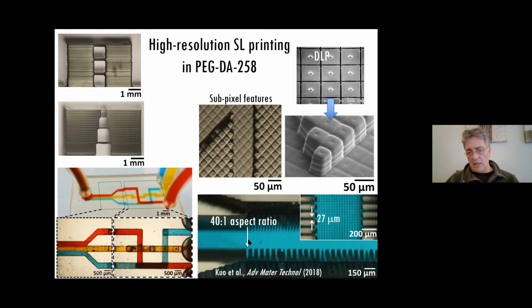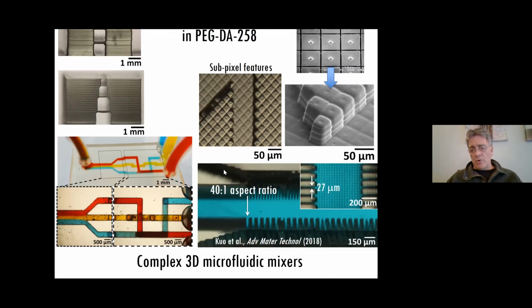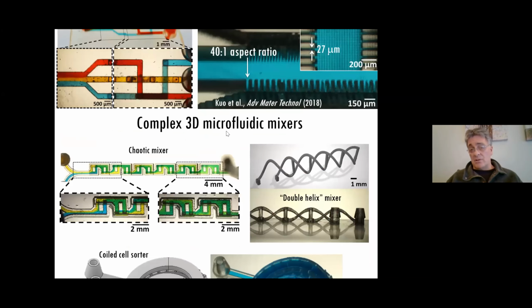And you can see also channels that were 40:1 in height and then single pixel in width, because our projected pixel width is 27 microns. By the way, the ones that you see here are not the fault of the printing process. They're actually pixels that are broken in the STL file. There are problems in the STL files that need to be addressed by the industry, but that's something that we cannot address.